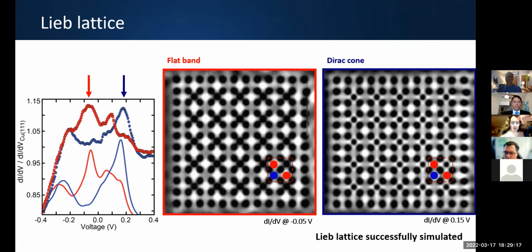Mm-hmm. So they will move between those, but basically from those localized spots. We could also do transport measurements, not on this specific system, but if we would create it in a clean room, and then one would need to create contacts, apply voltage and have a current go through. And then we expect that it would conduct well here in these blue peaks, but not in the red one, despite having many electrons here. But as they are trapped and localized, we expect that it won't conduct well.